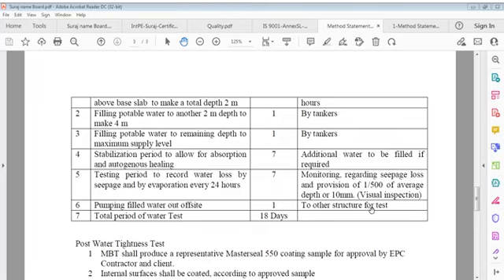Stabilization period 7 days, that's for absorption and autogenous healing. Additional water to be filled. In testing period, record water loss by seepage and evaporation every 24 hours. This was 7 days. Monitoring regarding seepage loss and provisions of 1 over 500 of average depth or 10 mm. Pumping filled water out of sites, so total period is 18 days. This is test.